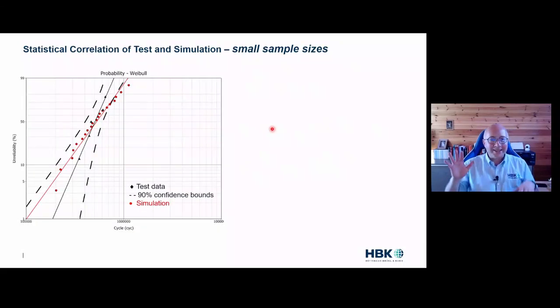So the first thing we can do is to compare our simulation that we have today with our tests. So even though there's a factor of 2 on the tests, we can still fit our probabilistic model. So the black points here are our 5 physical tests, and we can do our Weibull analysis here. And the dotted black lines, that's our 90% confidence bands. Now, if we superimpose all of our simulated curves, we find that for most parts, they fit really nicely in this band. They start to pop out a little bit above here.